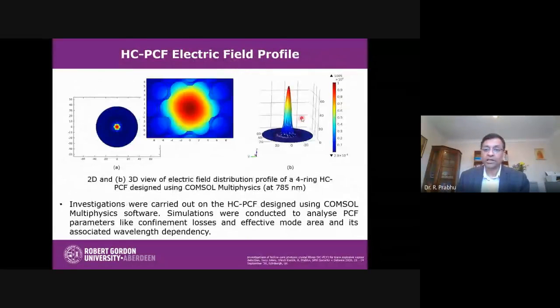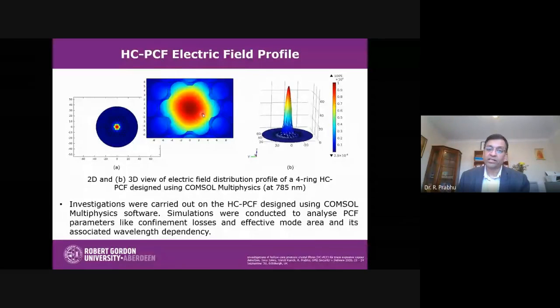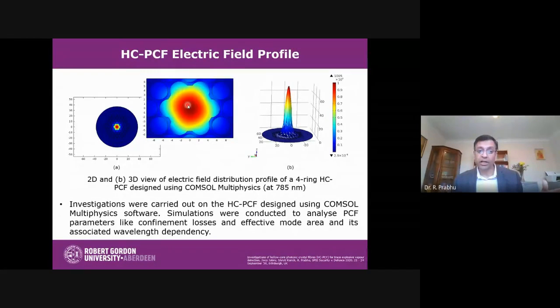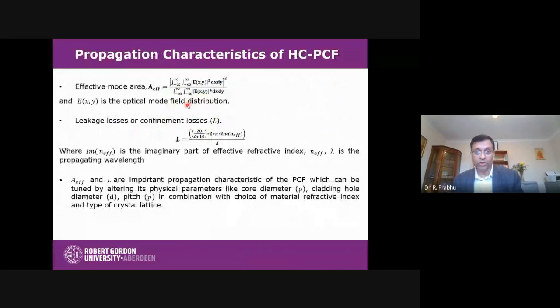Here you can see the electric field is increasing inside the core part, where the red shows a very strong electric field and it's tapering towards the edges. So we can enhance the electric field inside, and this will result in a stronger Raman signal. And we can use a longer optical fiber, using the length of the fiber to enhance the signal from the trace vapors. Again, this project is ongoing.